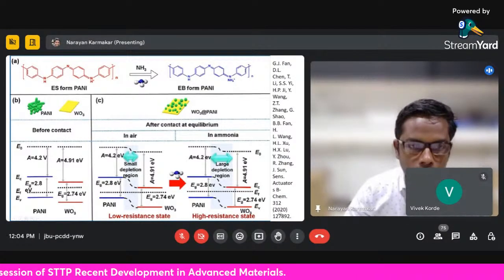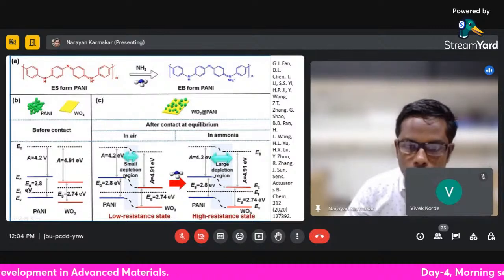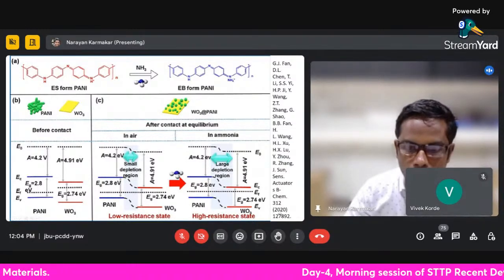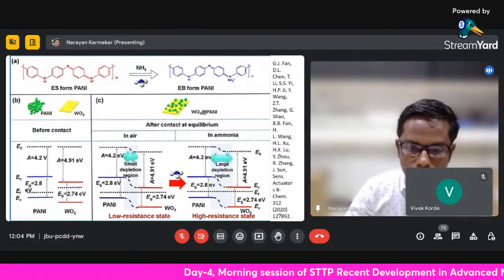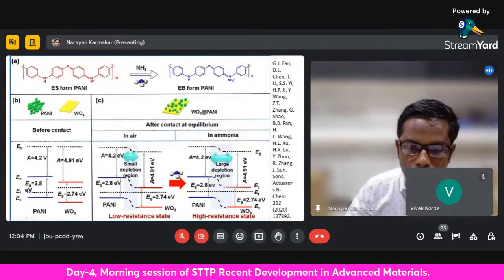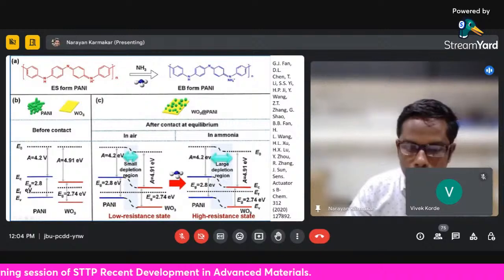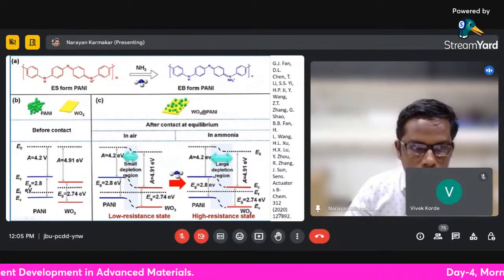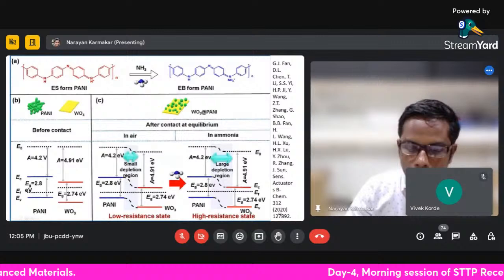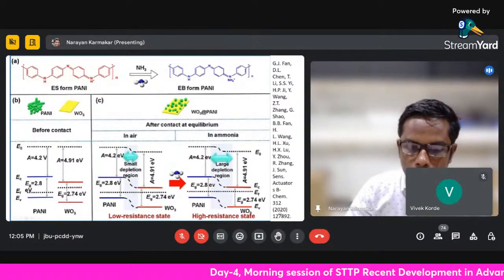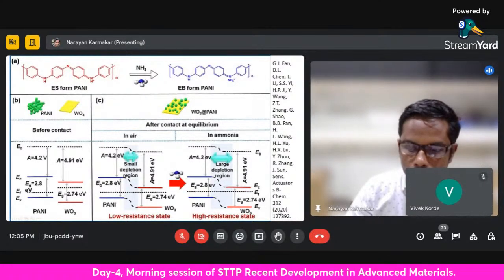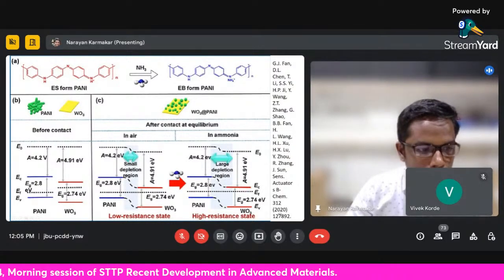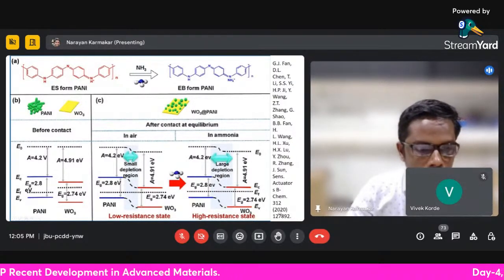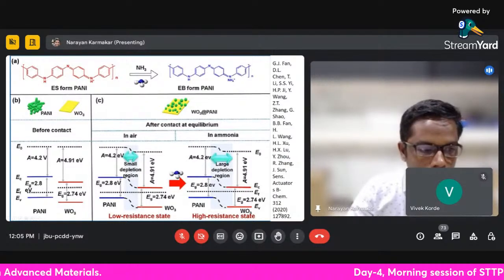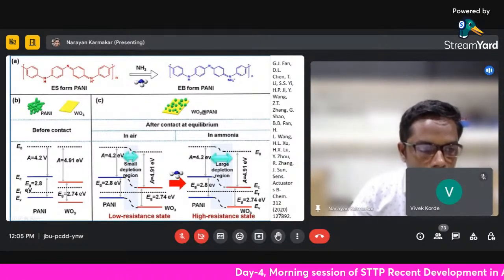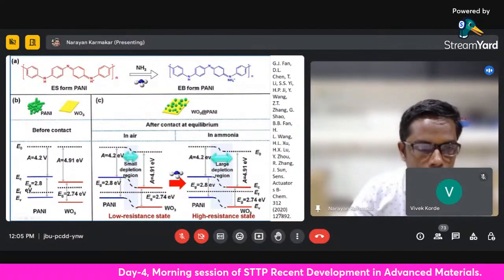So you can see that when they made a composite of this tungsten trioxide, the response overall increases. This enhanced sensing response was attributed to the modulation of the potential barrier at the interface, because tungsten trioxide is an N-type material whereas Pani is a P-type material. So when we have this interference, in the band gap, I'm not going into the detail of what is happening, but how they have selected the material in such a way that it matches with the HOMO and LUMO levels of this conducting polymer.